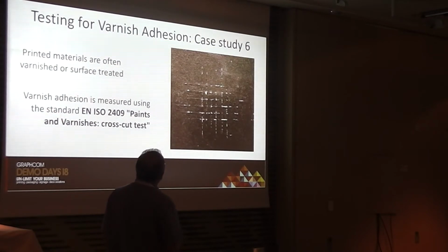Another test that we did that was an unusual test is to test the adhesiveness of the varnish, only of the varnish, not of the printer. Now this is a tricky test because you have the substrate, you have the printing, and then you apply the varnish. You have to make sure that you don't pull out the printed layer, but you only pull out the varnish. So it's quite a tricky test.